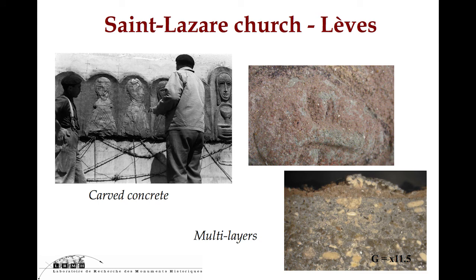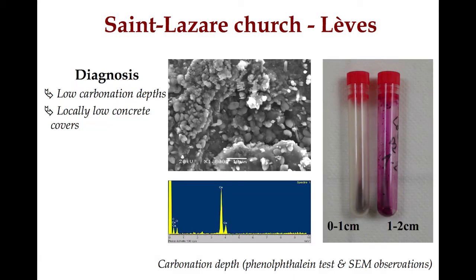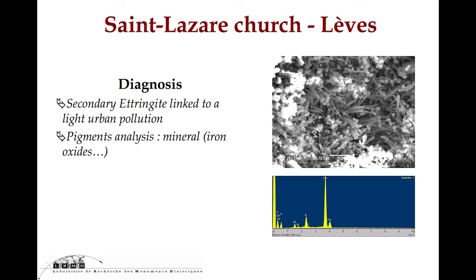So it was carved concrete. You can see here the artist with multi-layer concrete. So the diagnosis showed low carbonation depths with locally low concrete covers. The diagnosis showed secondary ettringite linked to light urban pollution, and the pigments were mineral with mainly iron oxides.